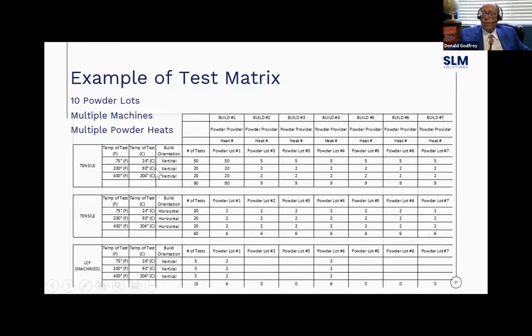And another thing, if you're doing Mar-M 247 or some Haynes alloys, you want to know, is there an orientation effect? So you're going to test the same number of verticals as you do horizontals to see if the material has a material property variation based on the orientation of which it was built. I can tell you with things like 625 and 718, you're not going to see more than 2% orientation effect. But with Mar-M 247, 738, and some other alloys, you most certainly will see a major swing.